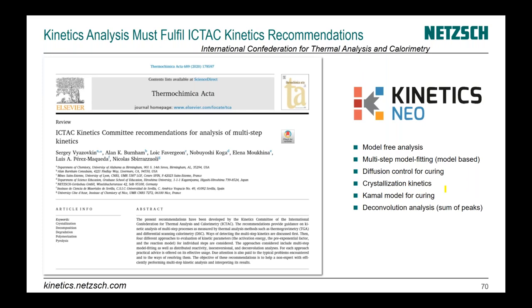The next question: what method do you recommend for simulating sintering processes? We recommend to use the model-based method because model-free doesn't work here. For model-based method, because usually sintering consists of reactions of N-order type, and after that during sintering some recrystallization and crystal growth happens, and therefore the last one or two steps could be reactions of Avrami type for nucleation and crystallization.